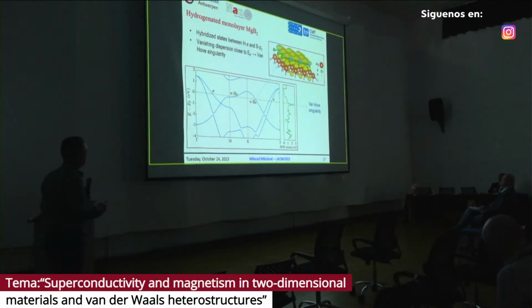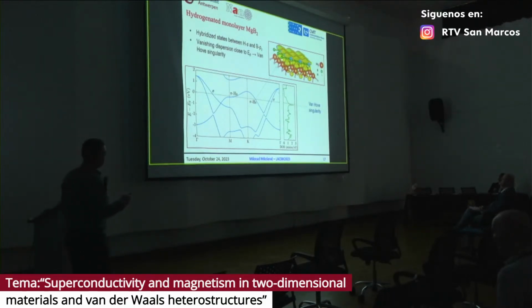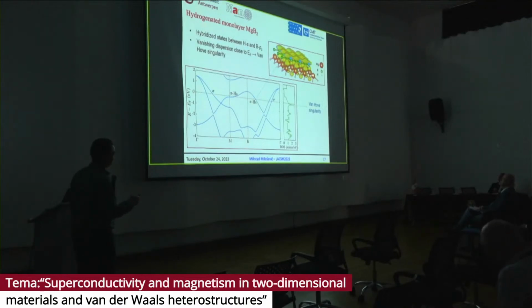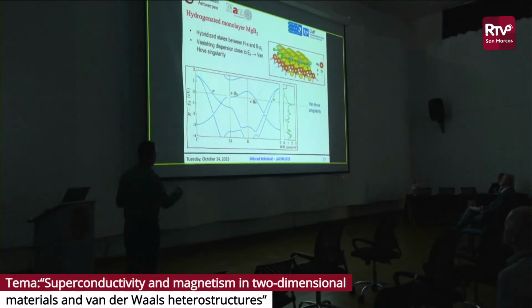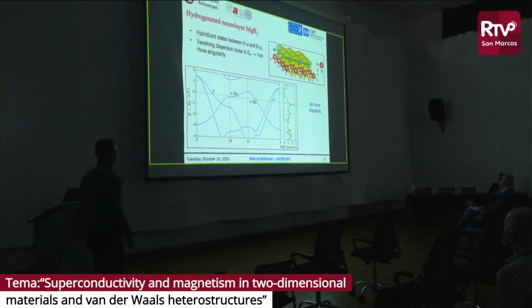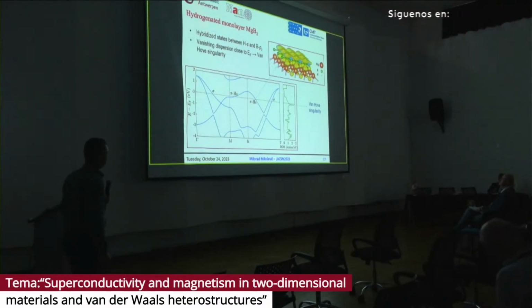So we added hydrogen to MgB2 monolayer. Sorry, this is upside down. So this is boron, this is magnesium, and this is hydrogen right here. And what we get now is this hybridized hydrogen band that crosses the Fermi level and carries a lot of density of states. This is the density of states. There is this one van Hove singularity that's also very close to the Fermi level. If you could bring this to the Fermi level, you would have even more density of states that contribute to superconductivity. But even as such, hydrogen contributes a lot of electronic states for superconductivity in this material.